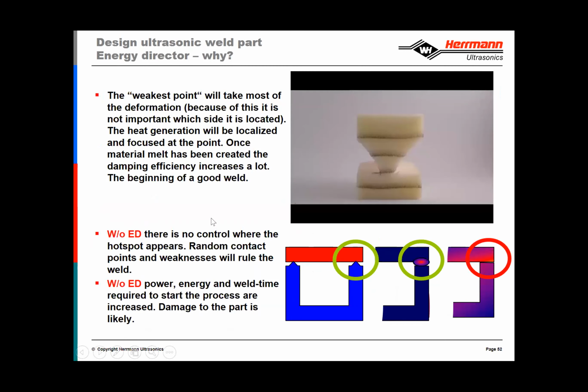So again, the energy director should be the weakest point. This is the part that will take the most deformation. It should be, again, sharp, and the heat generated will be localized and focused on that point. So this little video depicts that with the application of force. So you can see that the deformation is happening right at the point of contact and not as much at the top or the bottom of the part.